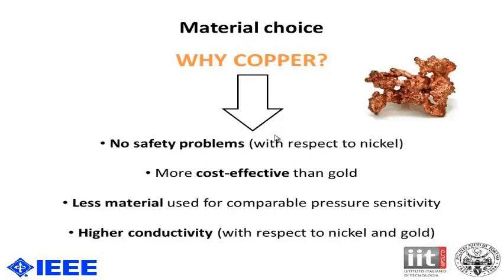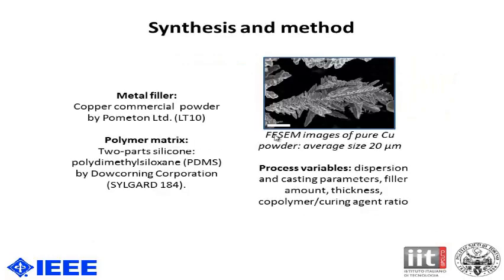So why did we choose copper? It is because it has no safety problems with respect to nickel. It is, of course, more cost effective than gold. Less material is needed for the same performance in sensitivity, and it has a higher conductivity with respect to nickel and with respect to gold. So we used a commercially available metal filler.